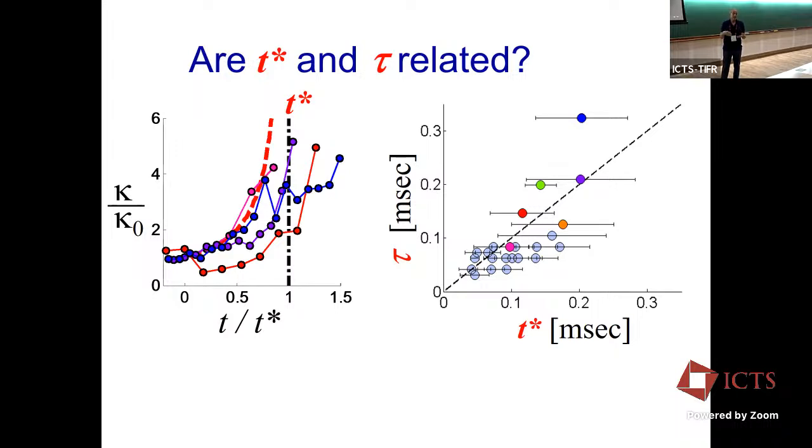But we need a finite perturbation the farther we are from the threshold for the oscillatory instability. So that triggered the onset of the instability, this K2. And now we gave the answer for why microbranches are micro and they don't just keep going. Because what we find is that these microbranches increase the fracture energy. They locally curve the crack front. And this curvature is actually unstable and creates a singularity. This singularity creates a cusp that has basically infinite curvature at its tip.